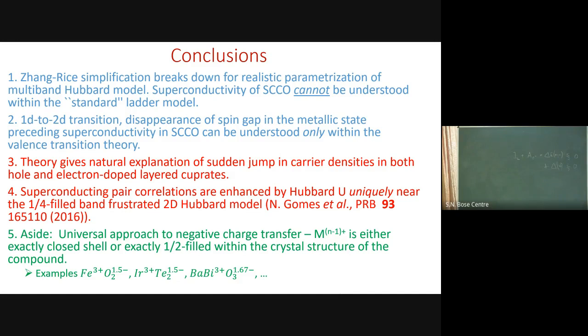But these are not isolated phenomena. They are all related. And I am claiming that it is also related to copper oxides. And if you were a BSc student, and somebody told you barium bismuth oxide is a superconductor, strontium ruthenate is a superconductor, lanthanum cuprate is a superconductor, and you didn't know anything, you would have said the superconductivity is due to oxygen. If you didn't know anything, then you would be right. Now, why is this important if this is right? This doesn't even touch the field of ferromagnetic superconductors, which is 50 years old.